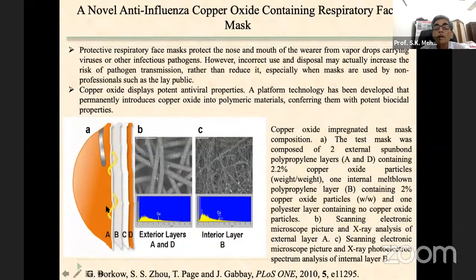They have 2 external spun-bound polypropylene layers, A and D. You can see A and D, these 2. They contain 2.2% copper oxide particles, weight by weight. Then you have the melt-blown polypropylene layer, which contains 2% copper oxide nanoparticles. And then you also have a polyester layer containing no particles. So this was the proposal, which nowadays has become very useful.